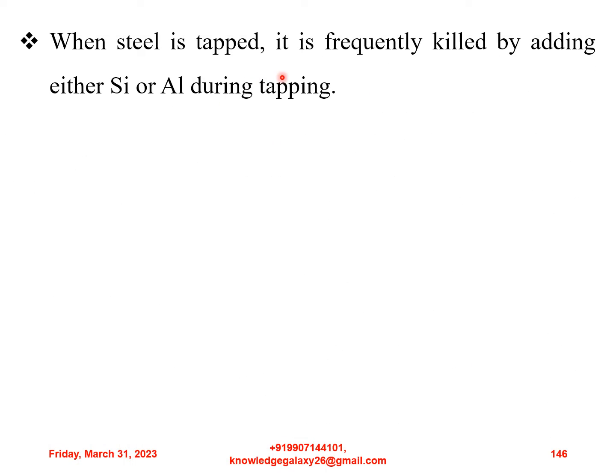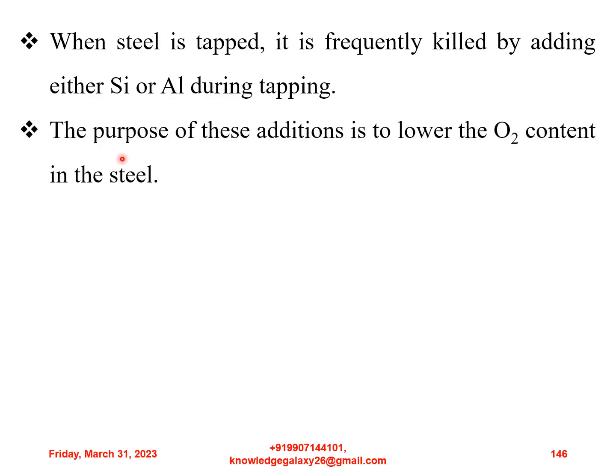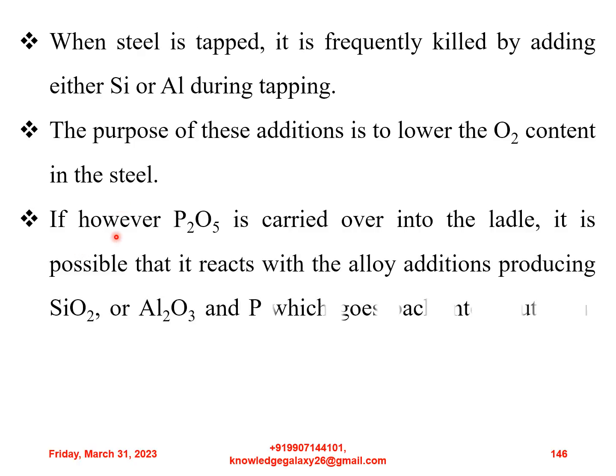When steel is tapped, it is frequently killed by adding either silicon or aluminium during tapping. The purpose of these additions is to lower the oxygen content in the steel. If, however, P2O5 is carried over into the ladle, it is possible that it reacts with the alloy additions producing SiO2 or Al2O3 and phosphorus, which goes back into solution in the steel.